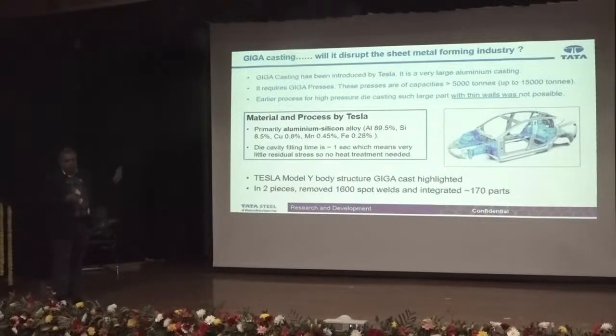Now the problem is, all of us know that high pressure die casting is not a new process. The only limitation was the size of the component and the wall thickness you could make earlier. That problem has been solved by making very large presses, which can pump in the liquid or molten aluminum at a very high speed. After that problem was solved, IDRA, an Italian company, developed that press. Now there are Chinese companies which have come up with presses up to 15,000 ton. Okay, and now see, what is the impact of this?